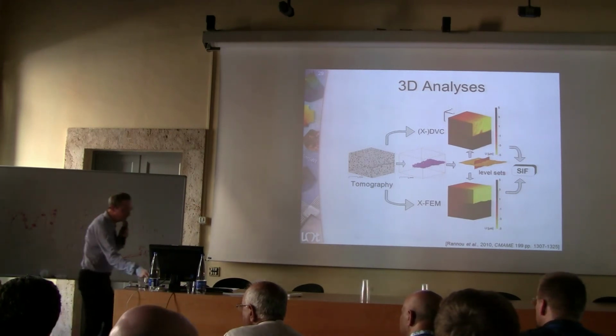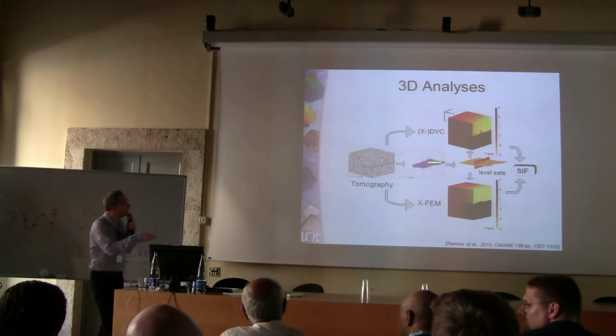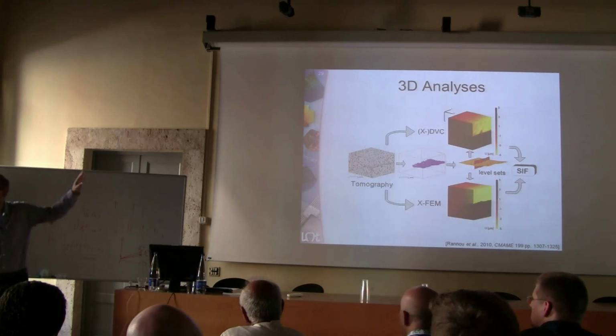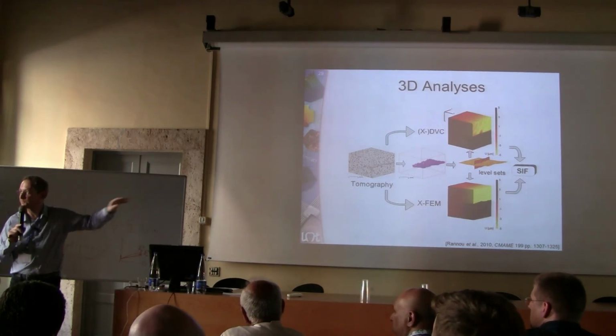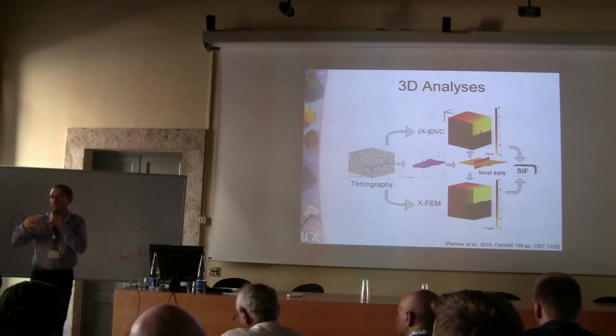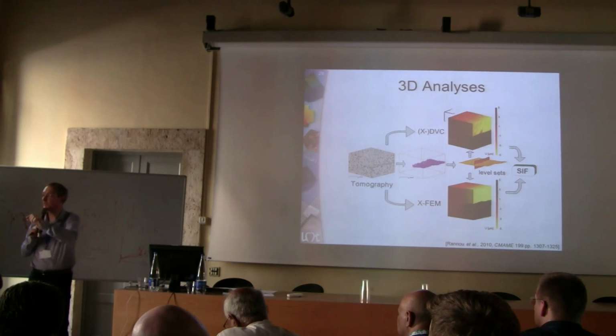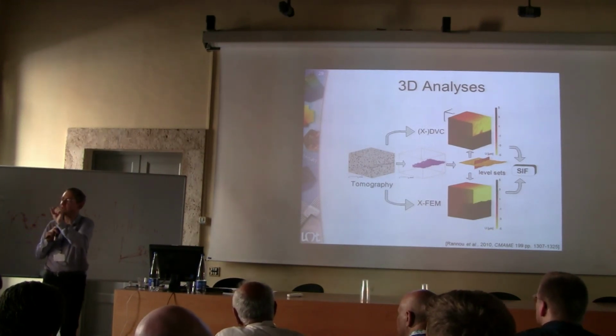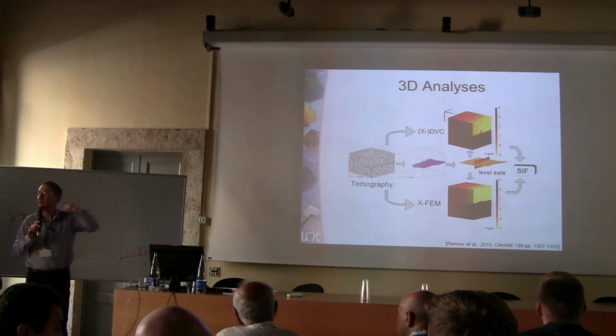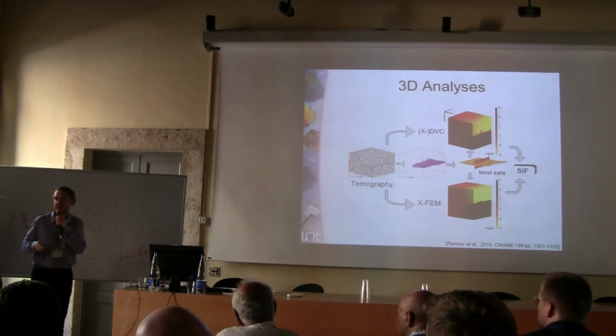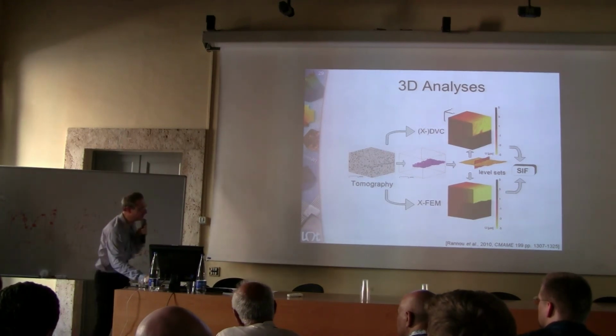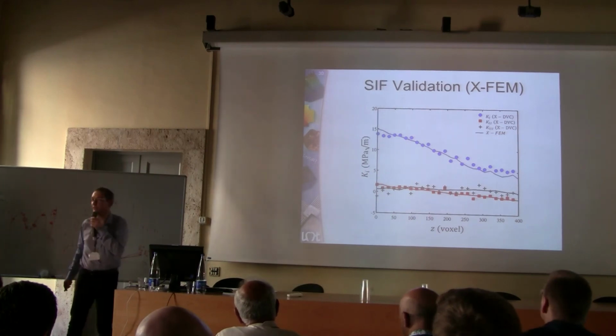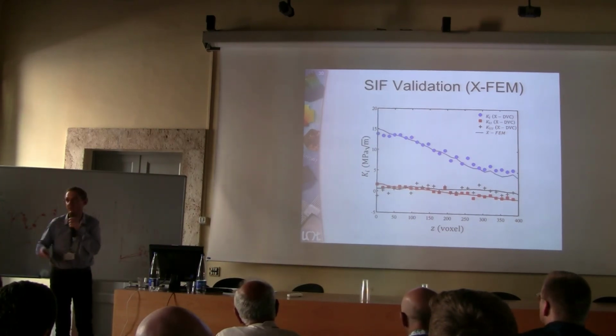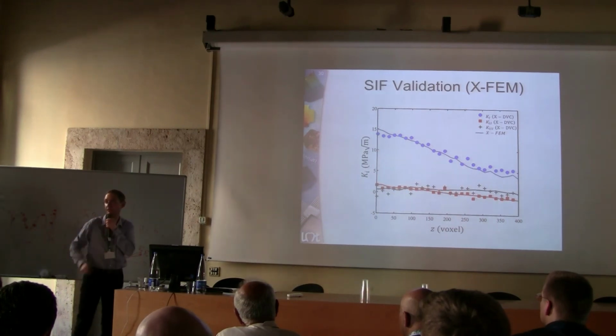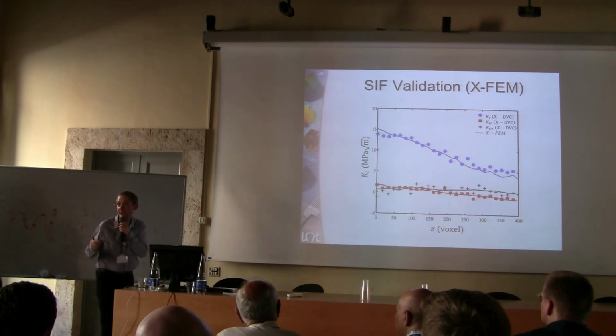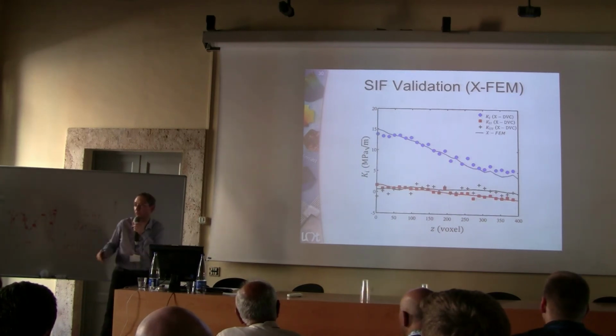Yes. Even though I didn't show it, we had another experiment in which we did exactly the same type of analysis, but for a larger load level, which meant that you had yielding that extended a bit more than in this particular case. And you could then see that something was wrong, in the sense that the agreement I've shown here was no longer the case, and you had an offset between numerical predictions and the experimental analysis.